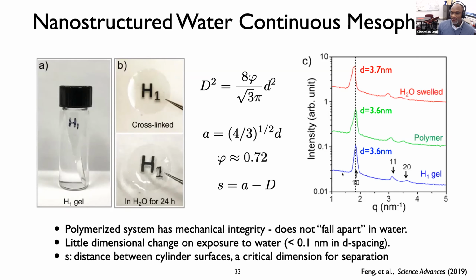And so what I'm showing here on the right-hand side is X-ray scattering data looking at the structure of that gel. So the system as it forms first with water present is a gel. After it gets polymerized by exposure to UV light, you can see the structure is unchanged. And then even after swelling with water, I think this was a 24-hour exposure in excess water, there is only the tiniest bit of dilation of the sample. So that tells you that really and truly you have a mechanically robust material in which the dimensions are well preserved from the gel all the way through to the water-swollen polymer.